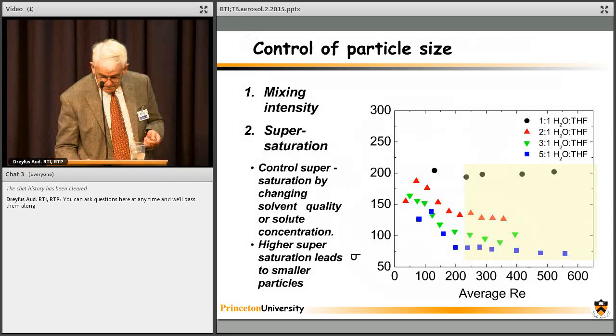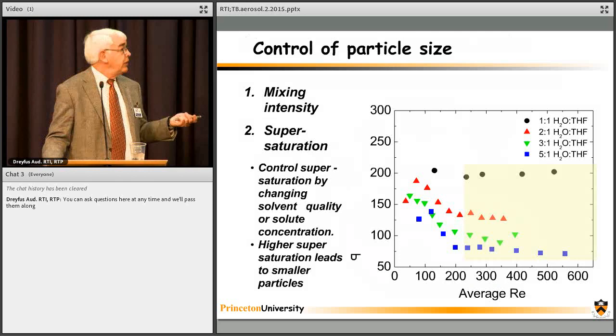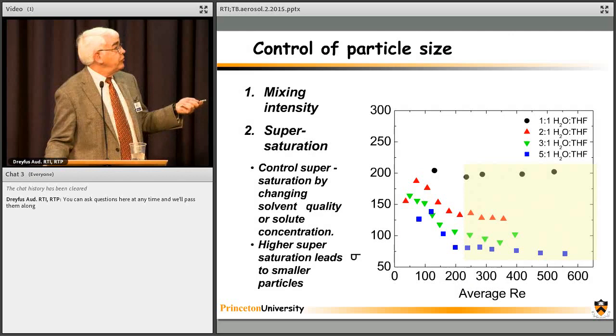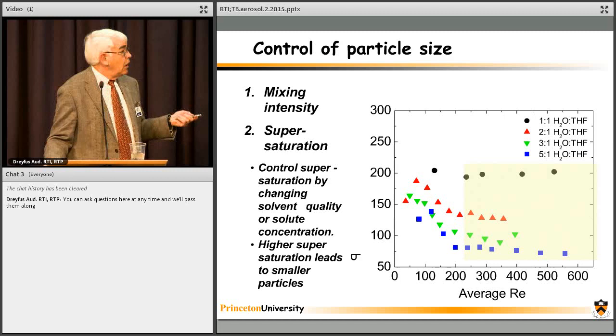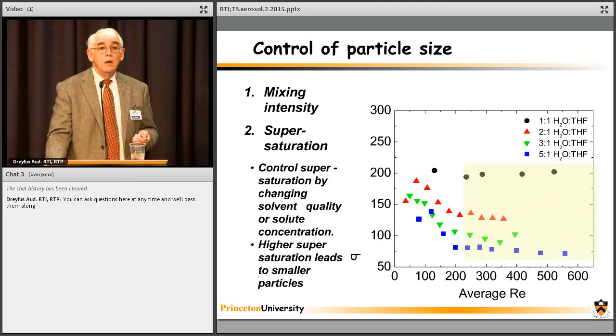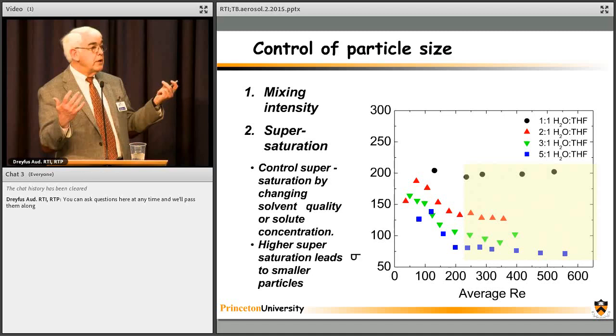So what's shown here is particle size. This is a beta-carotene sample, actually, and this is Reynolds number, which is the jet velocities. If we do very poor mixing, we end up with large nonspecific aggregates, and so they're too big. If we go up in mixing speed, you reach a mixing speed at which the particle size is independent of the mixing speed. So going to higher energy or velocity doesn't give you smaller particles. All you're doing is having the solvent exchange process be faster than that diffusion-limited aggregation process.